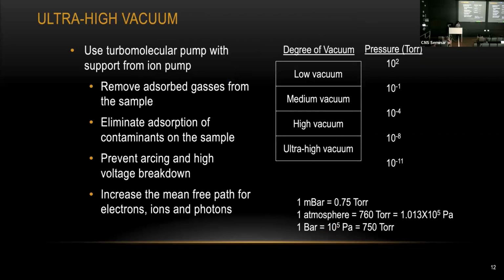Here is a slide showing what an ultra high vacuum chamber is. I give you a table of different vacuum ranges here. If you're doing some fabrication process, most of the time you're working in low vacuum or medium vacuum, between 10 to the power minus 1 and 10 to the power minus 4. If you're working on SEM or TEM imaging, you might be working in high vacuum, 10 to the power minus 4 to 10 to the power minus 8. But for surface analysis, since we are very sensitive to any air molecule or contamination, we need to work in the ultra high vacuum chamber, typically between 10 to the power minus 8 and 10 to the power minus 11 torr.